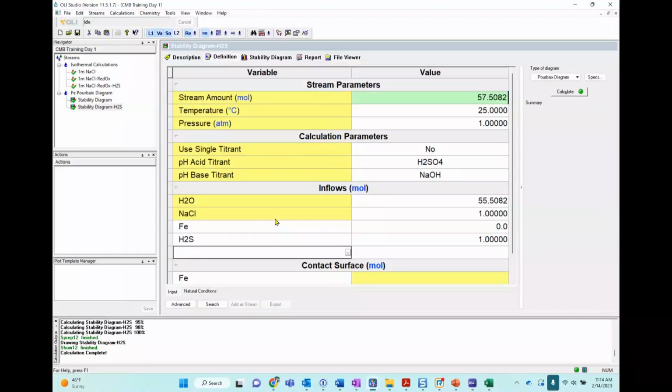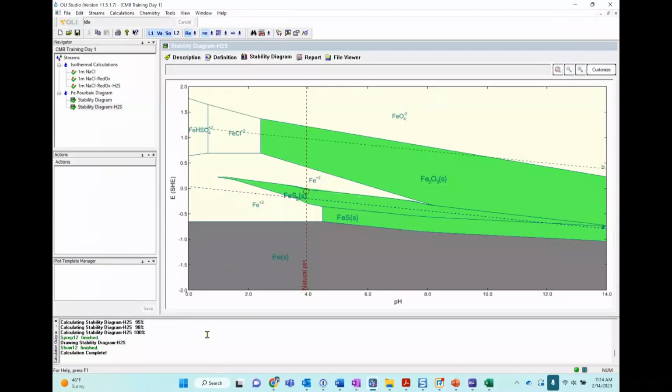Well, it depends. I've had laboratories where they do not want to see any chloride complexation, specifically at low pH values, like around 0 to 2 pH. And that is a complication in the lab where they have chloride cross contamination. So the reason why I use sulfuric acid is to avoid that complex formation.